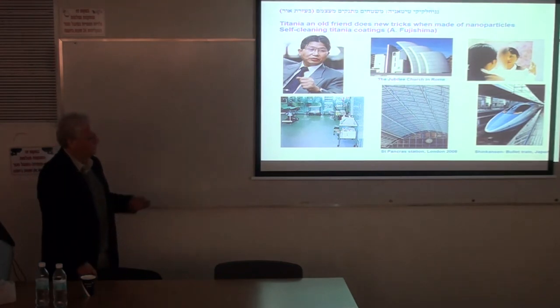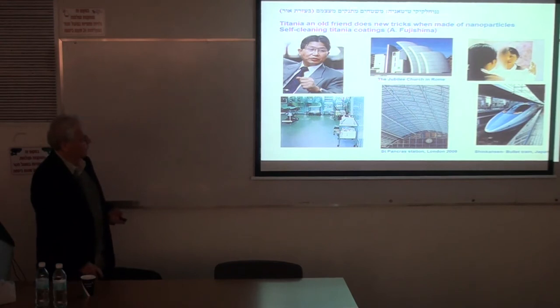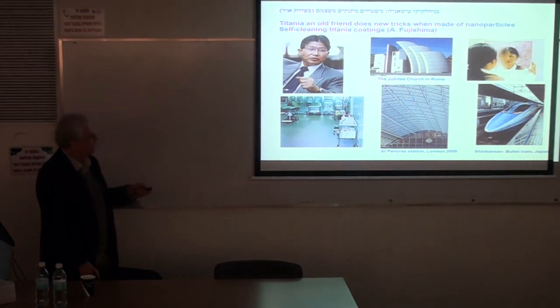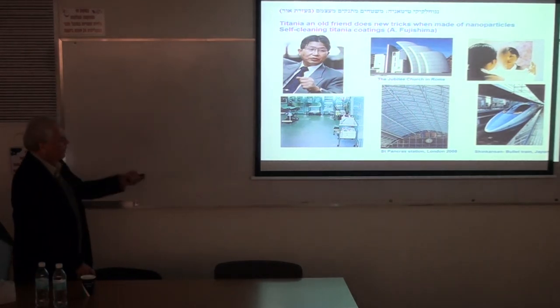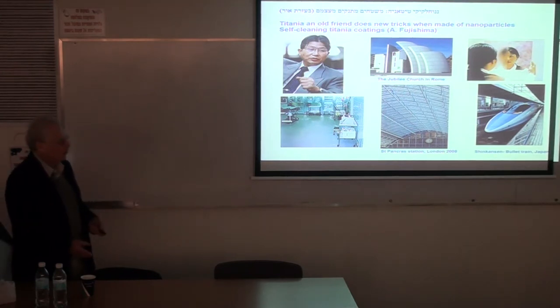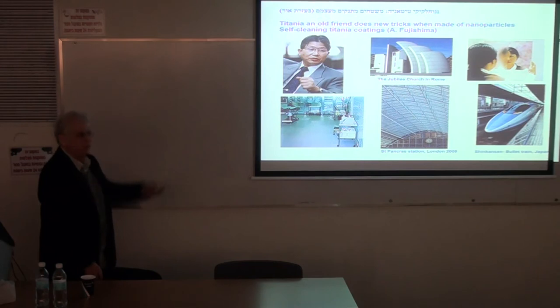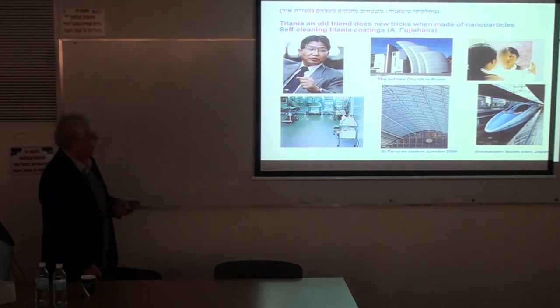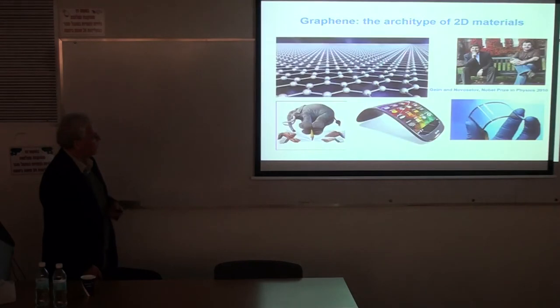you see how the anatase titania nanoparticles are powerful oxidants, and they can keep the surfaces very clean for a very long time, provided you wash them from time to time. So here's a recent example that I collected of these self-cleaning titania nanoparticles. It's a commercial product and technology that after 40, 50 years has gone into nanotechnology, and there are now a number of companies manufacturing these ceramic plates for self-cleaning surfaces. So this is another example of a self-cleaning surface.